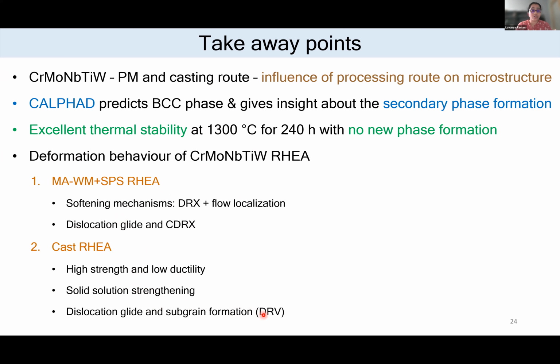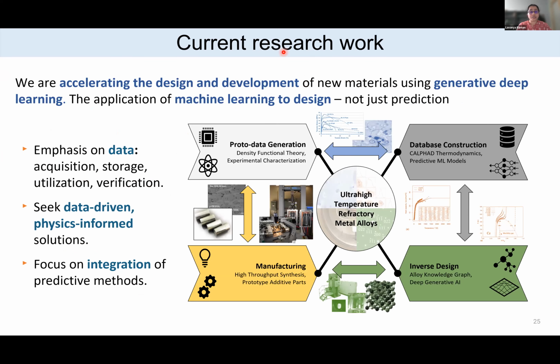So this is what we have done so far, majorly on one composition. The current work focuses on using machine learning to design these alloys. We give all the information from literature to the database, and we use certain models to design alloys depending on the application, that is, what your yield strength or creep resistance should be, depending on those data. The deep learning and CALPHAD high-throughput calculations will give us these compositions, which will be made using vacuum arc melting or a fast process, and then the properties will be studied. So this is a way wherein we can use computation or simulations to reduce the amount of experiments that have to be done.